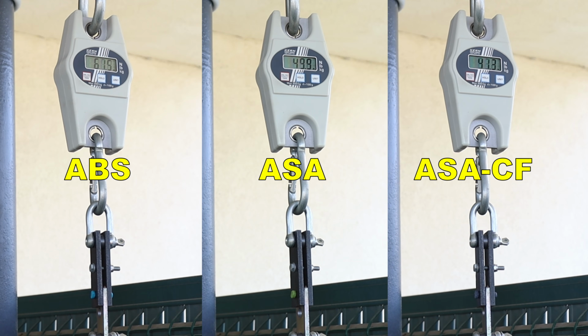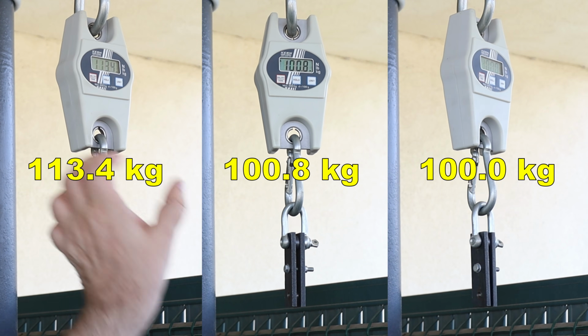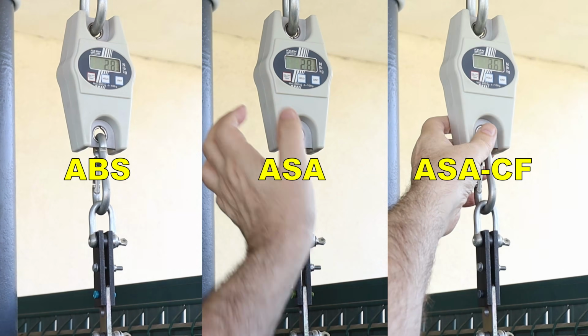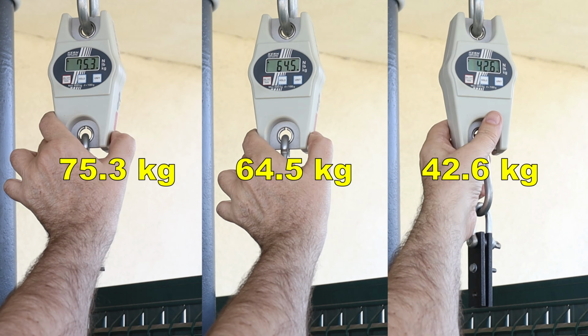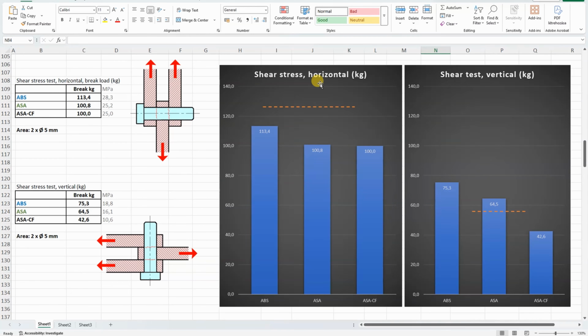Shear test, these are printed in horizontal position. Shear test, vertically printed objects. Interesting, in horizontal position the ABS is the strongest. Usually fibers help in this test, but if you watch the numbers, the ASA-CF is the weakest, though of course very close to the regular ASA. Printed in vertical position, here the layer adhesion is important, and of course the ASA-CF was quite weak, and ABS and ASA are above the average line.